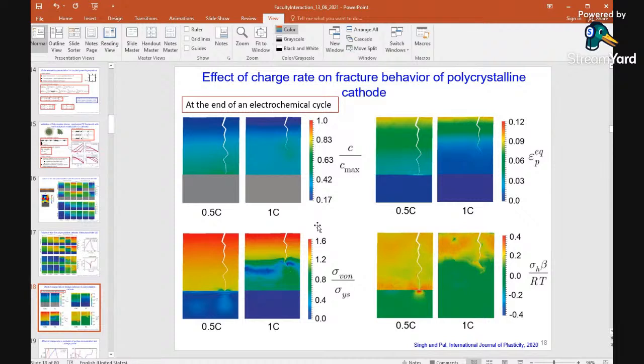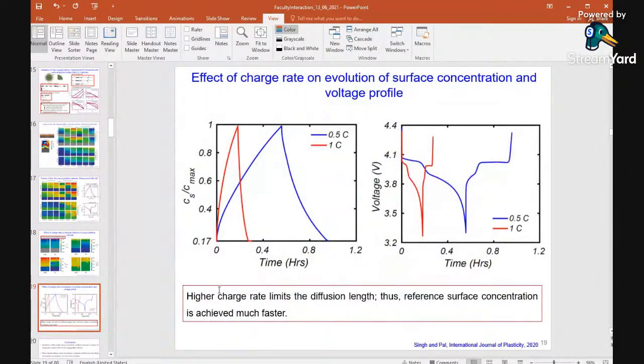And this is due to the plastic deformation. So the plastic deformation is distributed over the entire domain, which is holding together the structure. And when there is de-intercalation, this plastic strain is creating the tensile field, which is cracking the body, and that's the way we can see the difference. Okay, and this difference is reflected again for the charge discharge cycle. We can really connect these two aspects, how this charge discharge.